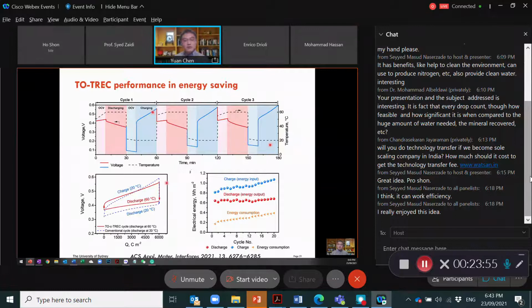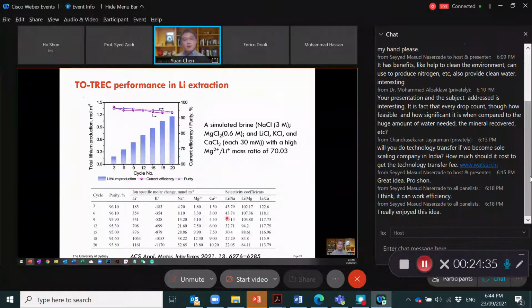And this is basically the voltage change on the low temperature and high temperature condition. And here you can see this is the energy input we need to put in to charge the cell, and this is the energy output we take out from the discharging process, and here the energy consumption. So compared with the cell, if we don't change the temperature from 20 to 60 during the discharging, we can save about 20%. There's a lot of energy lost from the reactor because we are not fully insulated, but even using this very small scale lab cell, we can very easily save 20% of electrical energy used to extract lithium.